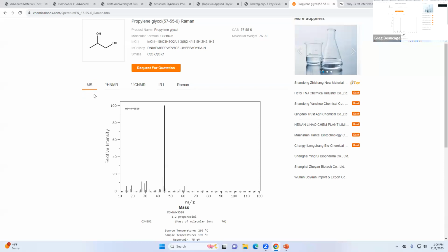Mass spec's pretty useful. From that, if you have your metals or you have some ceramic like a rock or silica, you can't do this with it, you have to take it and put it into HF, which one drop will kill you. Basically, you put it into this Teflon thing with HF, and then you put that into a microwave and cook it for a long time. Then you take it out, and then you've dissolved the rock into whatever.